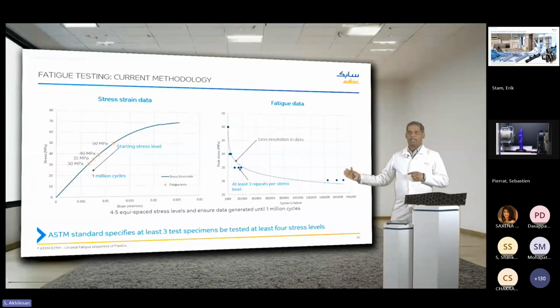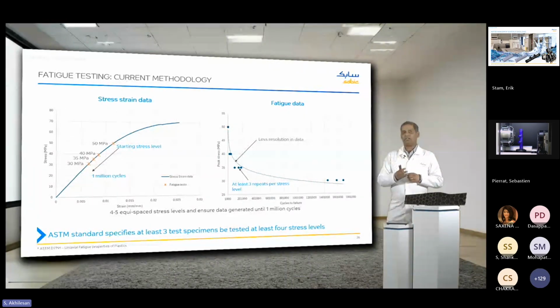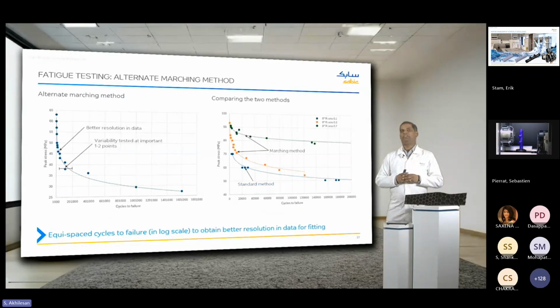This characterization is good for general characterization of the fatigue properties of a material. As you can see, the data points are quite coarse, and this results in inaccuracies during modeling. Hence, we have been looking at an alternate marching method. This is based on the suggestion from Hexagon, where we conduct fatigue tests at equispaced cycles to failure or equispaced stresses until we hit 1 million cycles.